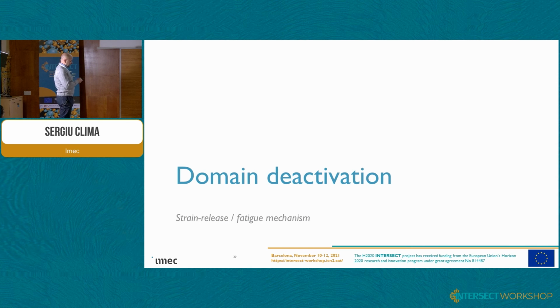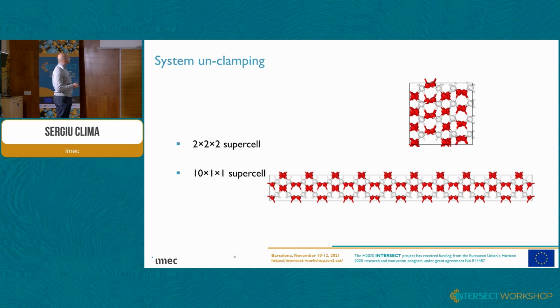Let me go about some interesting observations that could be attributed to the fatigue mechanism, for example. So if we simulate a model that has a cubic supercell, then we constrain the material and it cannot wiggle. So as you'll see later on in an elongated supercell model, we cannot go too high because then simulation time increases too much.